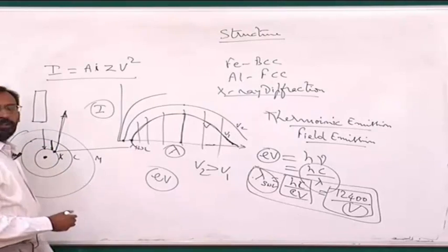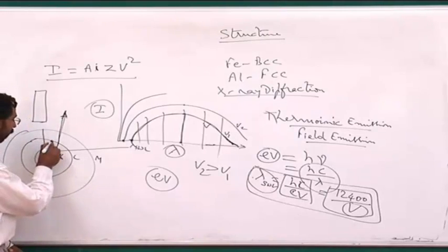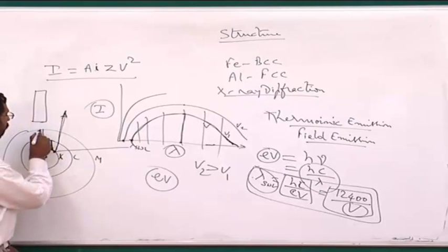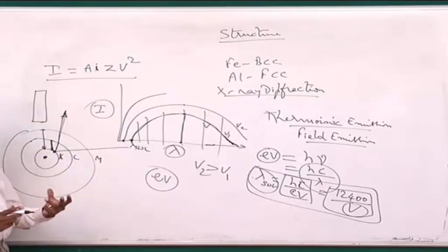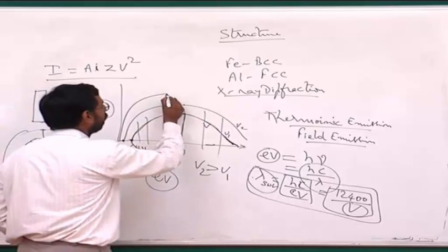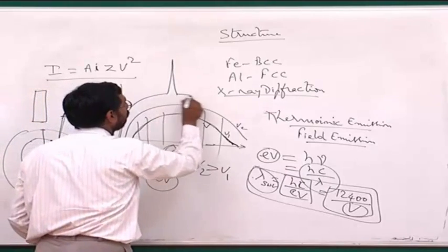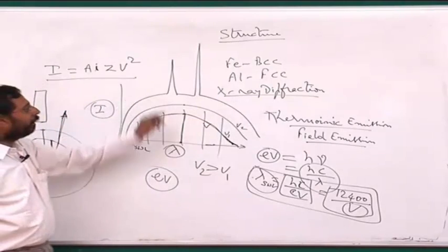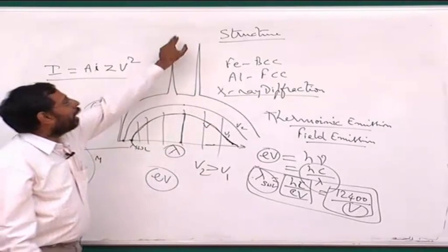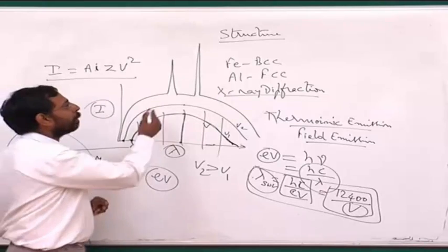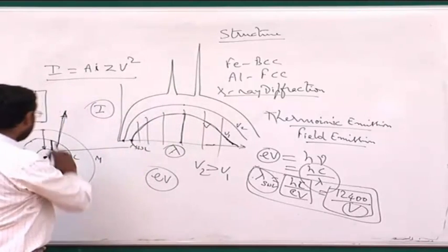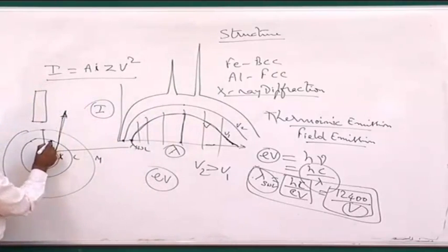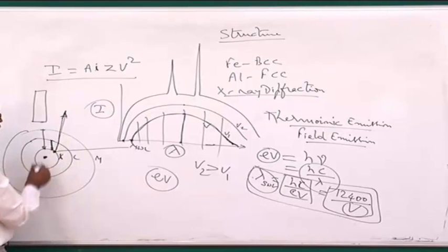And that is when you get, because the energy differences between these shells are quantized, we can get particular, specific wavelengths of radiation, which we call characteristic radiation, depending on which shell the electron is falling from, which shell it is falling to, and in which material.